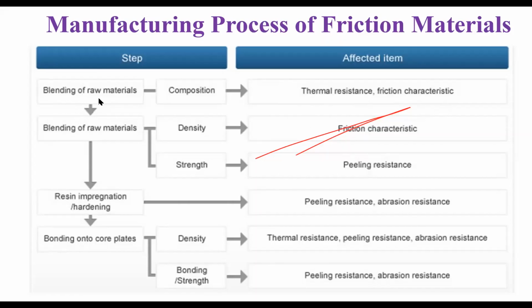And when you're going for a blending of the raw material, you also need to see the strength and the density of the raw material in such a way that it has peeling resistance. It does not peel off. It is basically stuck to the clutch plate. During the operation, when the clutch is rotating, the peeling strength should be much higher. It should stick itself to the clutch plate. It should not peel off. And again, you also need to ensure that the friction characteristics are met for a particular application.